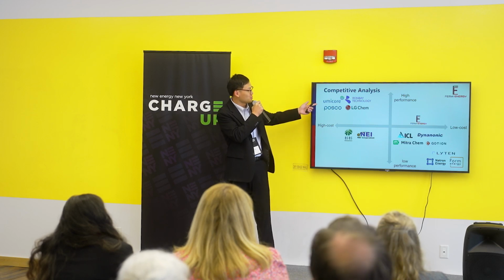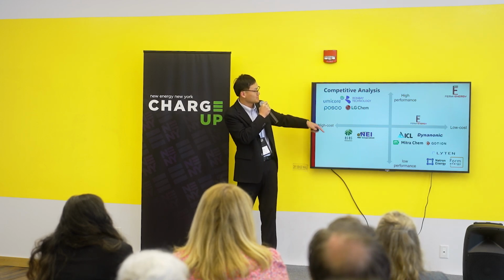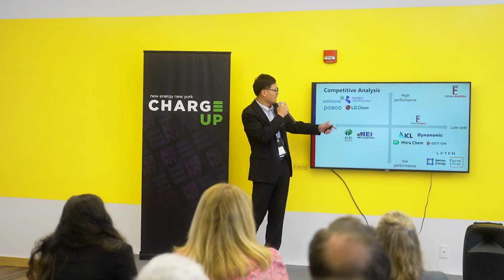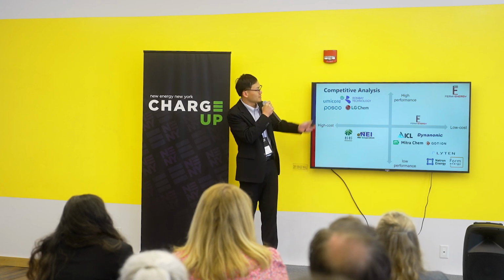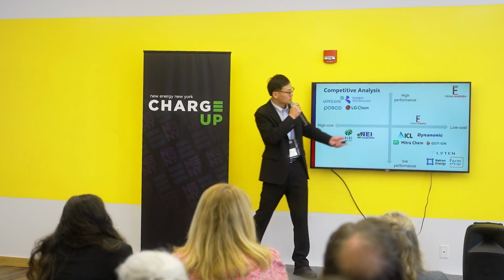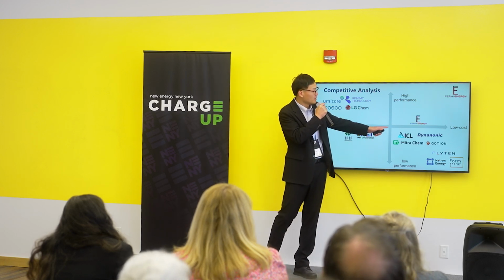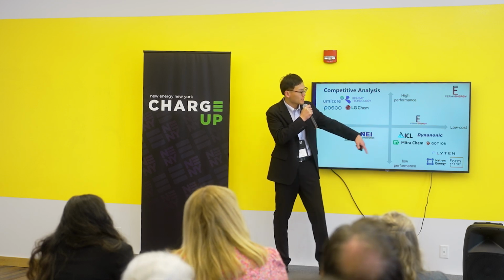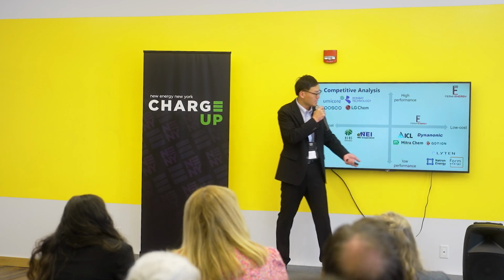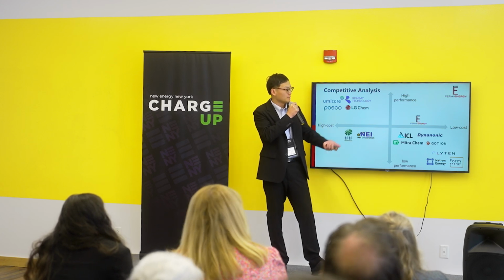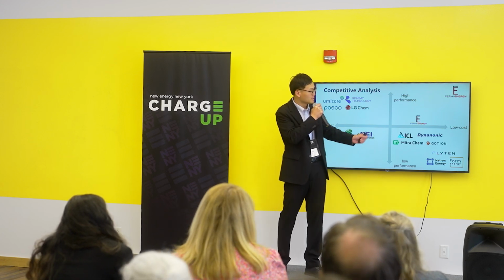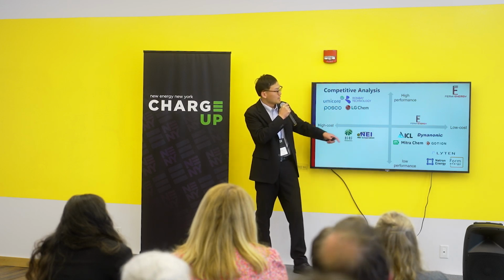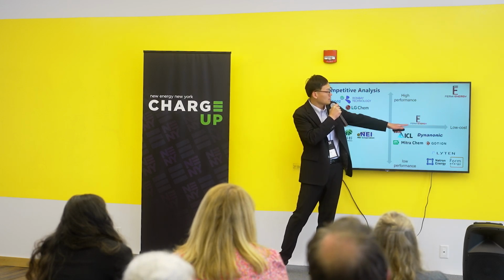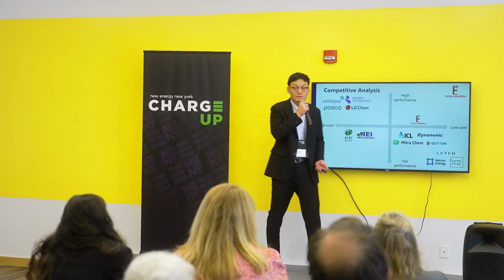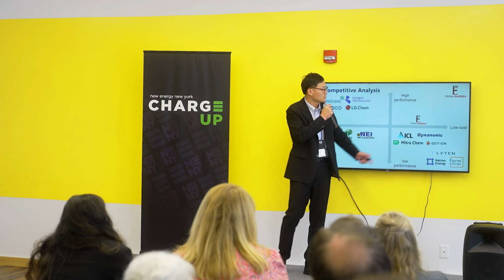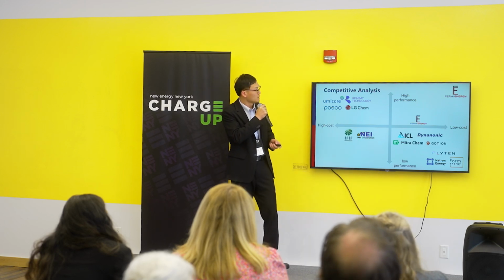You can see for the nickel-rich ones, they have high cost, high performance. Some of the cobalt-based ones have high cost, slightly lower performance than the high nickel ones. We also have lithium iron phosphate. They're on the lower cost side and lower performance. We also have some competing technologies such as iron air, sodium ion, or lithium sulfur. They claim to have the lowest cost, but the performance is also on the lowest side. And here we are proposing lower cost but slightly better performance than the lithium iron phosphate chemistry, and that's how we are going to compete with these competitors.